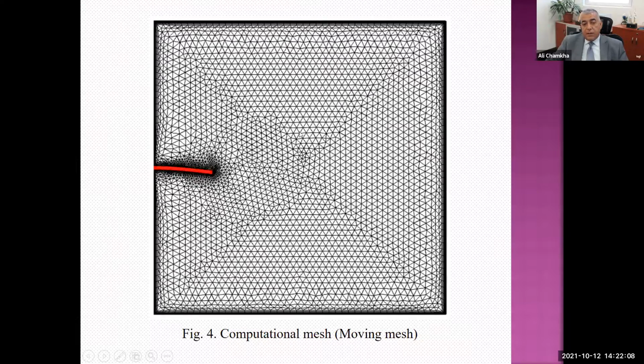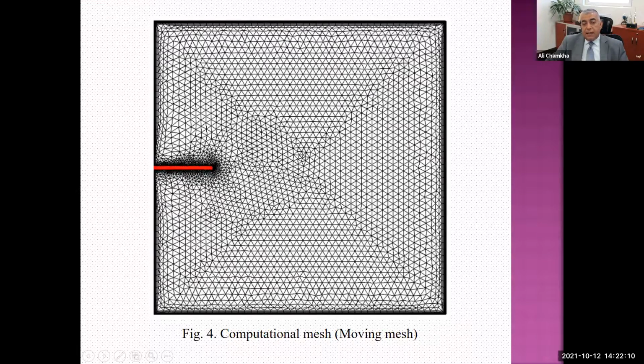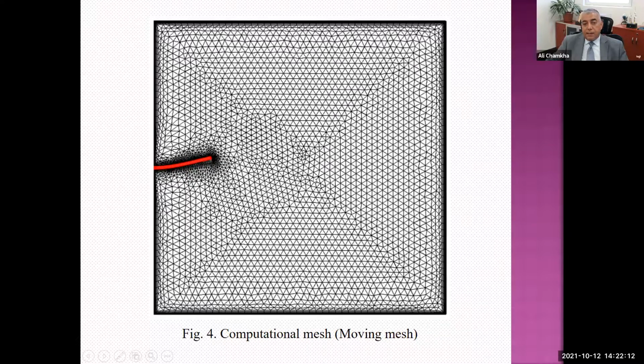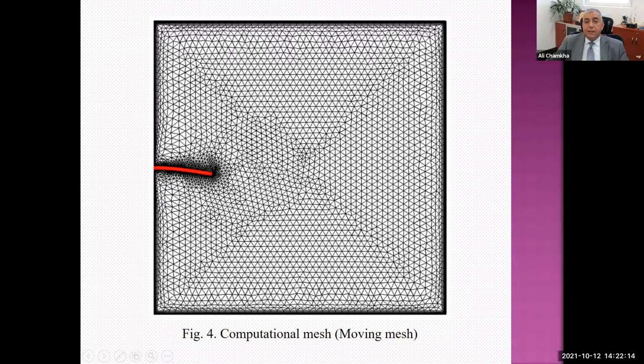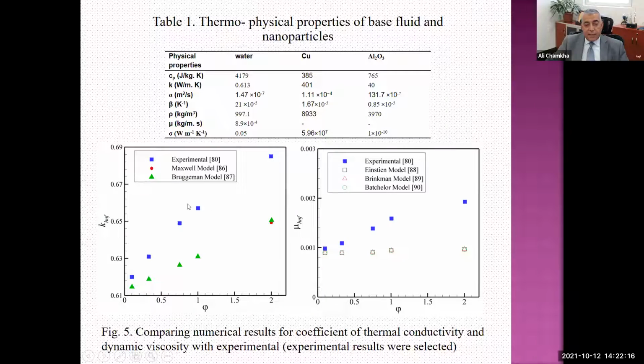You can see how the mesh is changing as this fin oscillates, so you have different meshing. These are the experimental data that we found for the thermal conductivity of hybrid nanofluid, and this is the viscosity, and that's what we modeled with a linear model.